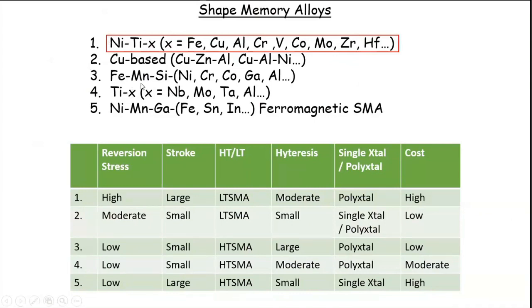And this, of course, is iron, manganese, silicon, nickel, chromium, which will be based on the stainless steel alloys, and it's very close to 9 chromium and above, or stainless steels. So of course, the stainless steel shape memory is an ideal shape memory, but you can see that basically the purpose of this is to get epsilon martensite and to prevent the alpha martensite coming out under stress. So that is the design of these alloys. It is something that is very cheap and very easy to make, but the difficulty is that it has a very small amount of strain, and so far, I think, a couple of applications have been done. It is still waiting for the big time deployment.